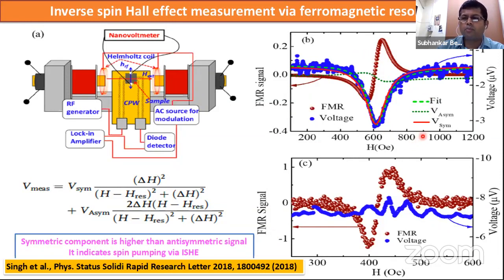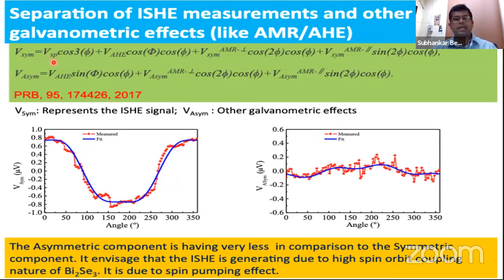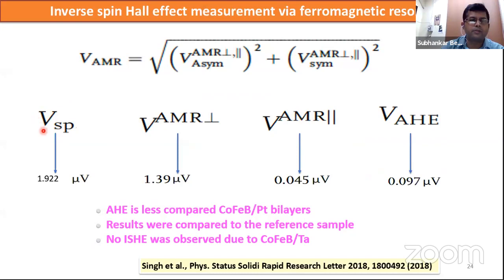And you can use this formula to decompose the symmetric component and asymmetric component. The symmetric component contains this spin pumping voltage and this anomalous Hall effect, anisotropic magnetic resistance, and other effects, and the asymmetric component, the other spin rectification effects. So the point is, if you make an angle dependent measurement over 360 degrees, really 2-degree steps, and you plot the V symmetric versus angle and the V asymmetric versus angle, using these formulas, you can now figure out the individual components. So we find the spin pumping voltage is the highest among all other spin rectification effects, and that's really nice that the bismuth selenide prepared by electron beam evaporation is actually exhibiting definitely high spin orbit coupling, which finally leads to this inverse spin Hall effect.